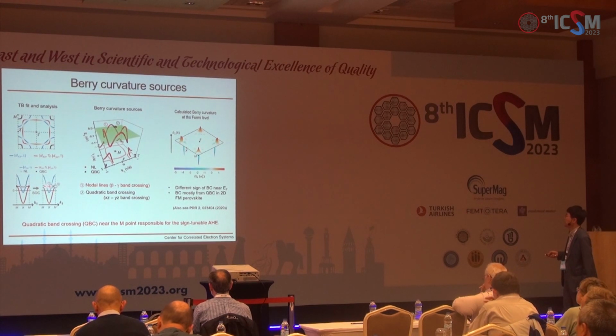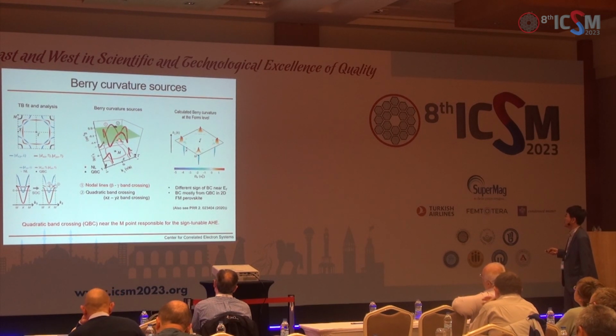So we can notice two. One here between gamma and beta and gamma band crossing here. So let's call that number one. And number two is hybridization between YZ and ZX. And this number one is shown here. This guy is a nodal line, and the nodal line is the Berry curvature source here. And also this quadratic band crossing opens up a gap due to spin-orbit coupling and has Berry curvature sources as shown here.